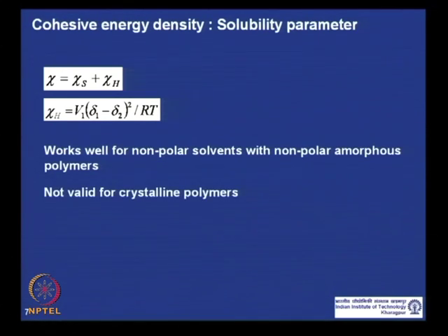It is not valid for crystalline polymers because this expression, or this approach we are talking about, talks about liquid solvent and liquid polymer, meaning amorphous polymer. So, if you want to dissolve a crystalline polymer, then you also have to include the contribution of the enthalpy of crystallization. In this case, that enthalpy of crystallization is not taken into account. So, that is why this approach is not valid for crystalline polymers; this is valid only for amorphous polymer.